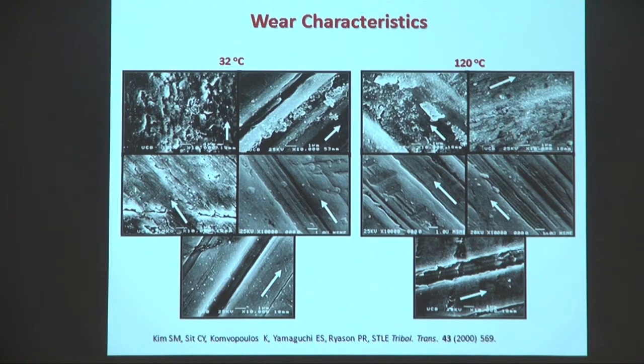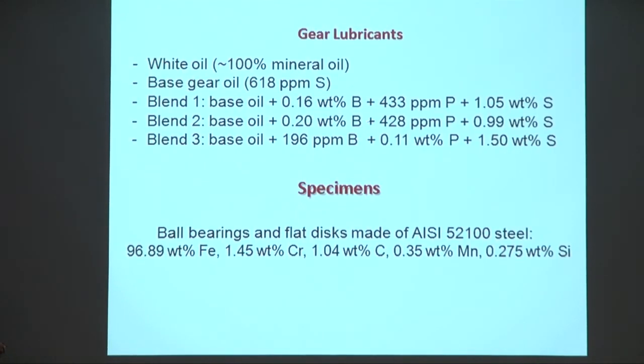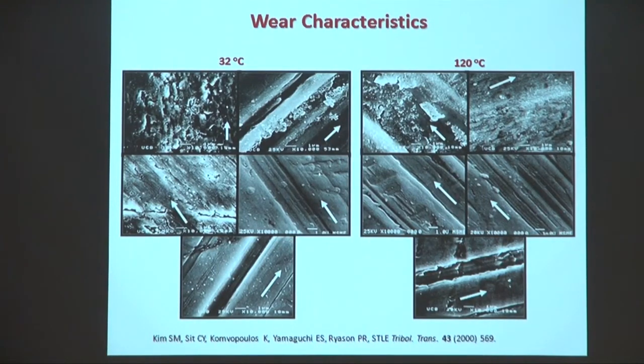In fact, blend 1 appears to be forming a film, but this film seems to be brittle and is cracking. No surprise, we have boron and very little sulfur in this film. And in these cases, we have reduced phosphorus and boron, but more sulfur, so these are softer films, so they undergo more abrasion.